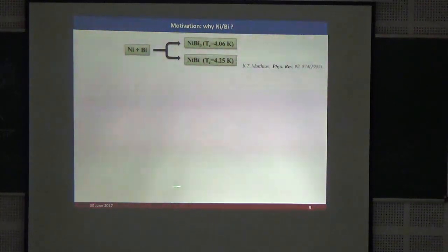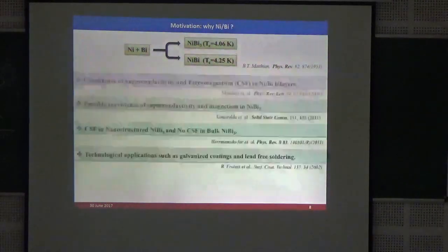So what motivated us towards the nickel bismuth system? Whenever you mix nickel and bismuth, you expect to get two stable phases. They are NiBi3 and NiBi. Interestingly, both of them are superconductors at 4.06 Kelvin and 4.25 Kelvin, respectively.